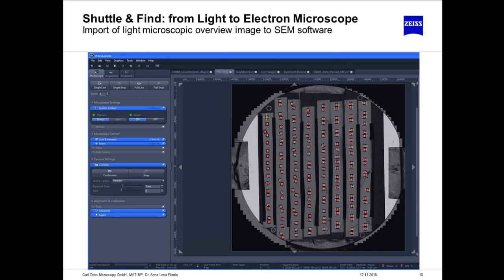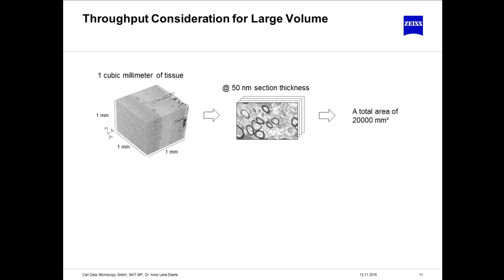But if we now consider the throughput, if we want to image a larger volume, like, for example, a cubic millimeter, it doesn't sound like too much, but in electron microscopic dimensions, this is a whole lot. So if we cut this cubic millimeter of tissue at 50 nanometers, just for the sake of easy numbers for the math here, as I said, you can go below that, like 30 nanometers. But if you go for 50 nanometer section thickness, this will end up with 20,000 sections. So in the end, it's 20,000 square millimeters that needs to be imaged.